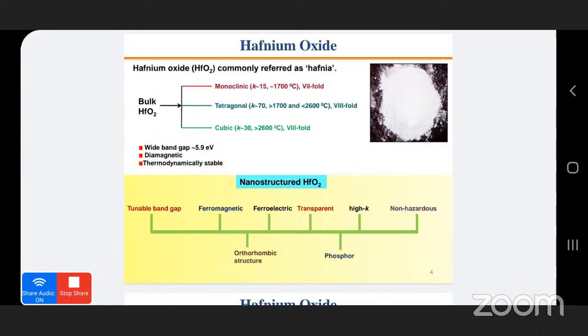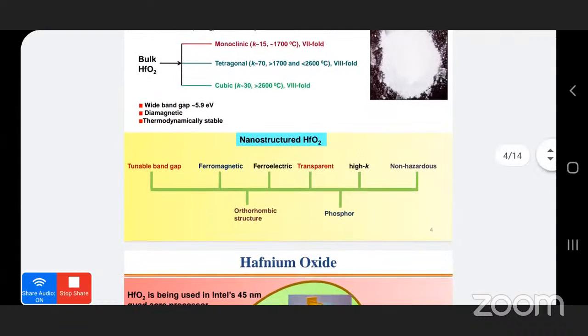But things really become very interesting when we move from bulk hafnia to nanostructured hafnia. Nanostructured hafnia shows very interesting phenomena, such as a tunable band gap. The nanostructured hafnia is ferromagnetic in nature, in contrast to the diamagnetic nature of bulk hafnia. It also shows ferroelectricity. Very recently, in 2011, ferroelectricity was observed in nanostructured hafnia thin films, and it has rendered a very potential application in the field of ferroelectric random access memories. Due to the wide band gap, it is transparent in nature. It has high K. It is also non-hazardous, so it also offers biological applications. The ferroelectricity has been observed due to the formation of the polar orthorhombic structure, and it is also a very good phosphor material.